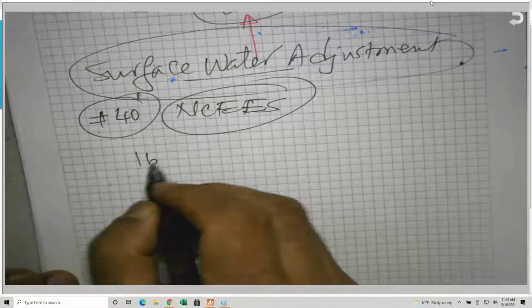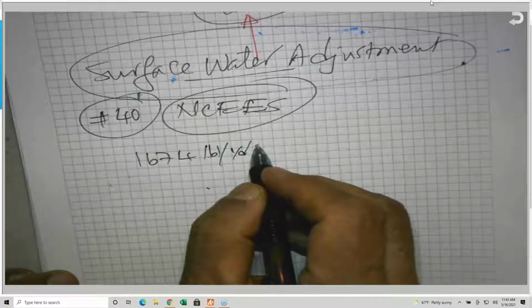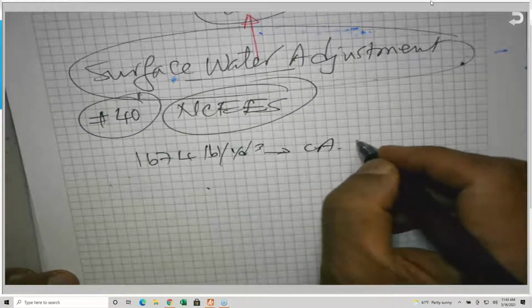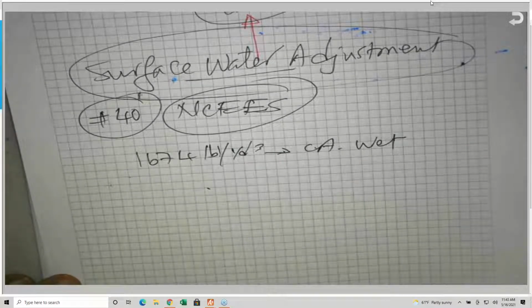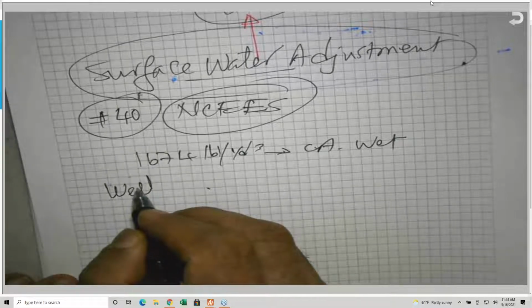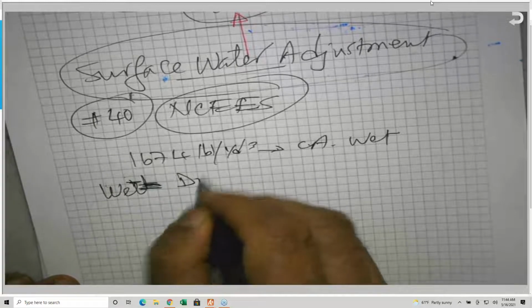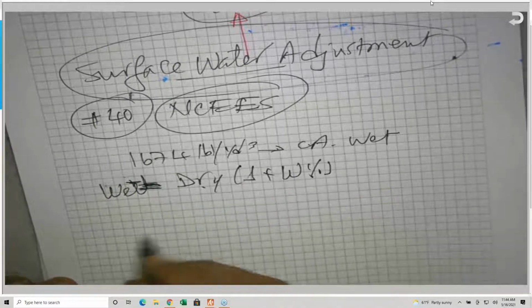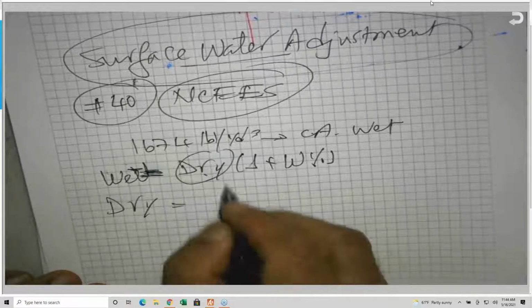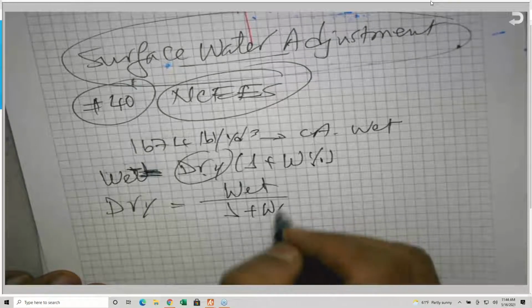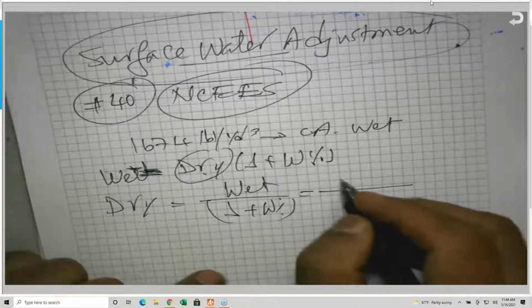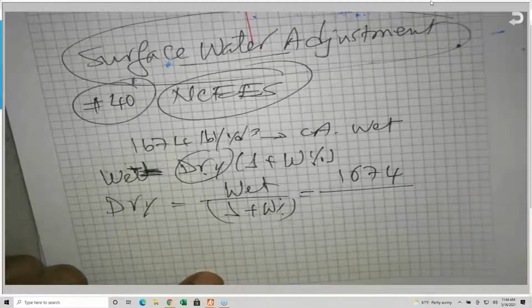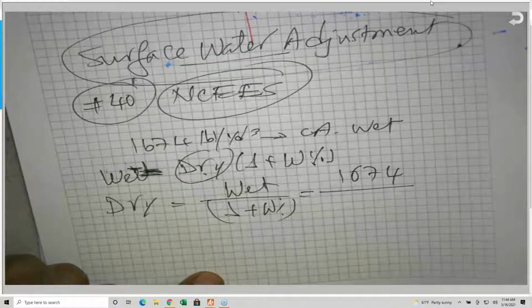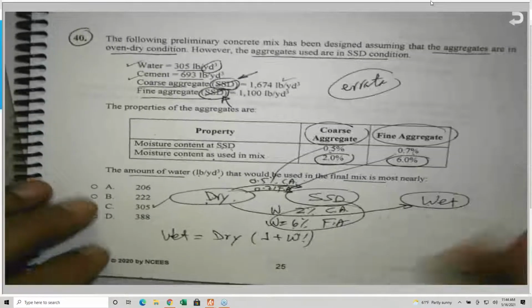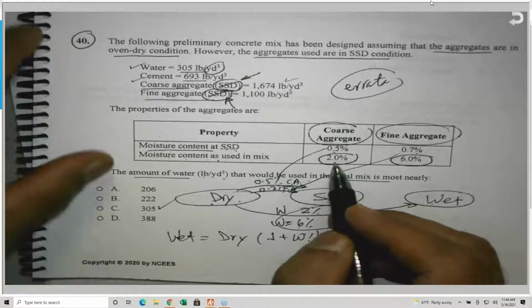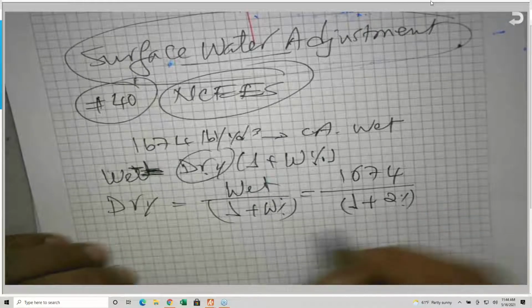So he added 1674 pounds per cubic yard of the coarse aggregate, which is wet, according to him. And we know that the wet is equal to dry times 1 plus moisture content. I need to get the dry weight. So the dry weight is equal to wet divided by 1 plus the moisture content. So the wet weight, how much he added? He added 1674 divided by 1 plus. How much is the moisture content for the coarse aggregate? It is 2%. So this will give me a number.